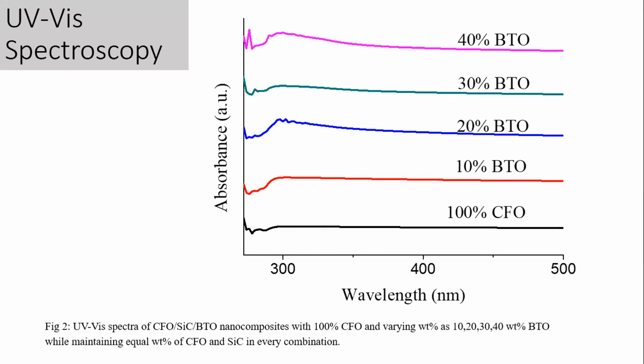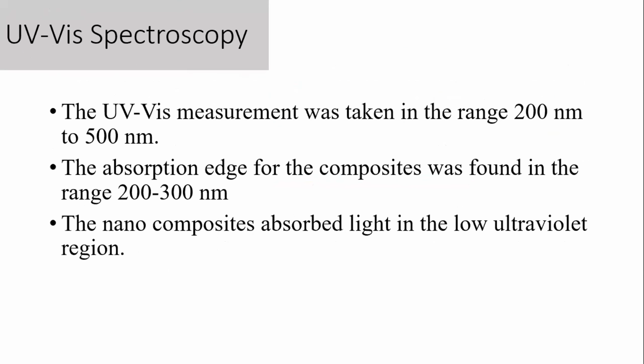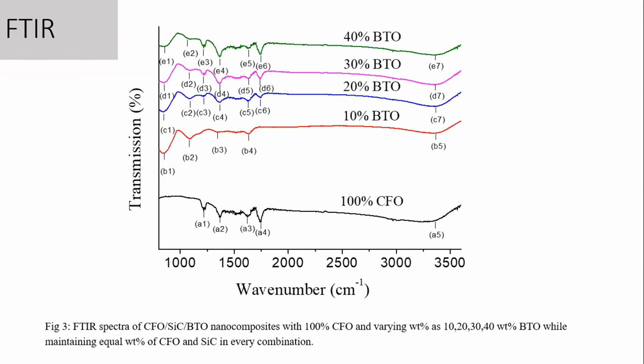Now, this is the UV visible spectra. On the screen, we have UV visible spectra in the range 200 nanometer to 500 nanometer. By this measurement, we found that the absorption edges for the composites were in the range 200 nanometer to 300 nanometer. We could conclude that the absorption of light is happening in the low ultraviolet region. So this was the first optical study that we performed. We are also trying to understand more about the UV visible spectra. The analysis is still under progress.